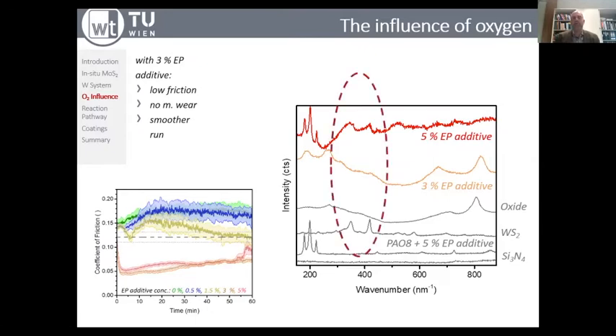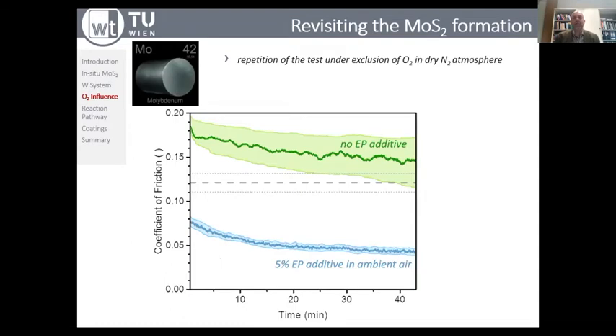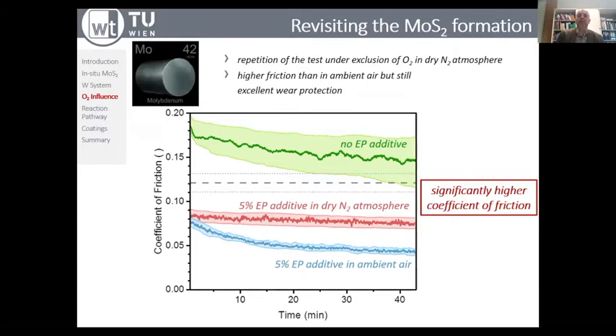And when we look a little bit more at that, we said, okay, now we understand this with a pre-oxidized substrate material, tungsten. What would also happen if we start revisiting the MoS2 formation? So we just exclude the oxygen from the test, and we do that in a dry nitrogen atmosphere. Just to remind you, we had the scenario before, no EP additive, and then we added the 5% EP additive under ambient air. So once you start, of course, doing the test in dry nitrogen atmosphere, you see the coefficient of friction goes down, but it is not as low as in the scenario before under ambient air. So there is a significantly higher coefficient of friction, and obviously, as I said before, the oxygen plays a very important role.